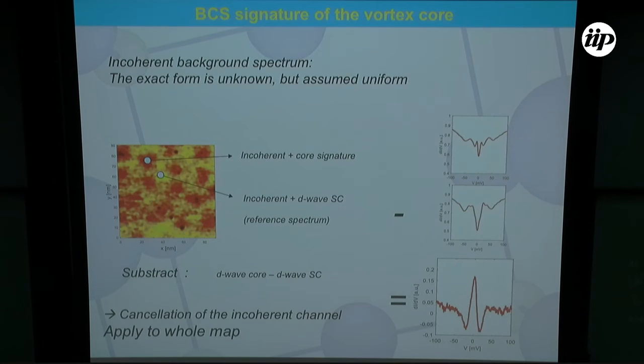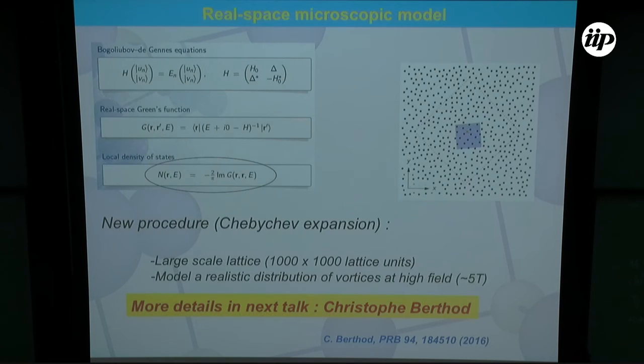So this is the measurement, but we need a model to compare this situation. We apply this subtraction procedure, taking one reference spectrum, to the whole map, and we now come to the model. I won't go into the details of this model, since the next talk of Christophe Berthod will focus on this topic. Just let me tell you that we need to measure the local density of states, which requires the calculation of the Green function. The Green function requires the inversion of a matrix, which can be quite tough to calculate if you consider large-scale lattices. In this model, we use a lattice of about 1,000 by 1,000 units, which was large enough to include a number of vortices corresponding to the 5 Tesla field we were using in the measurements.